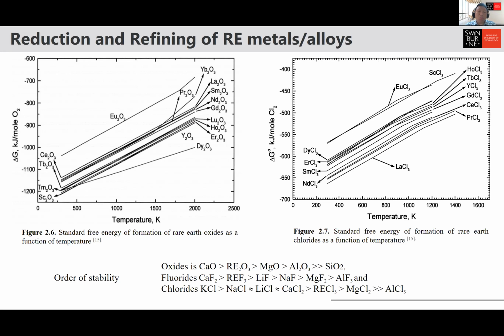So basically, that's why we use calcium as a metal reductant for these rare earth elements, right? This is also quite important because the rare earth oxide sits at the bottom, when you try to process these elements using a pyrometallurgical route, right? Mainly they will end up in the slag because they are pretty stable, and they lie with the magnesia, alumina, silica, and also calcium at the bottom there.